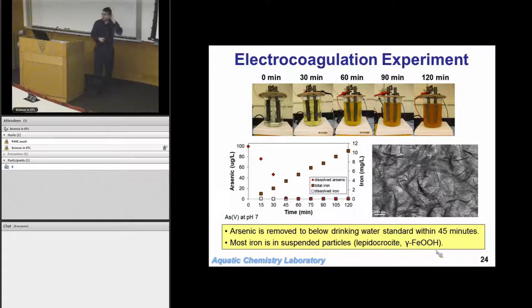So this is what we did in our laboratory. This is what this 1 liter reactor looks like as it goes through in time. You can see the iron oxide building up. This is concentrations versus time. The arsenic is in the red points here, and it starts out, we did these experiments at 100 micrograms per liter, comes down. Within 45 minutes, we're at a nice low concentration. We're probably below the drinking water standard in 30 to 45 minutes.